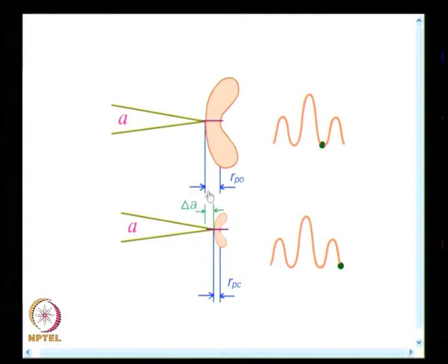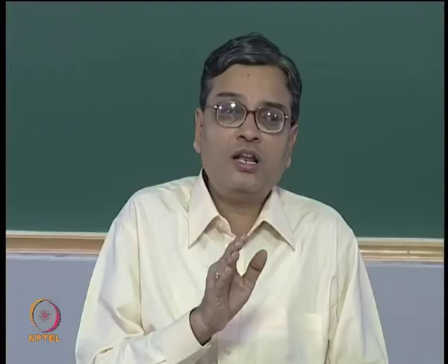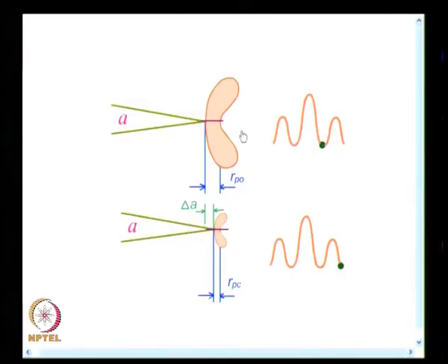Mind you, these are all highly exaggerated pictures. These are very, very small when you look at the actual specimen. For the sake of clarity, they are blown up and you have to respect it that way. So, what you have here is at the end of overload, what is the kind of plastic zone size you have. After the overload, only the crack and its plastic zone is shown. The earlier graph showed superposition of this diagram over this. Now, these diagrams are drawn one after the other to show the parameters. You will have delta A plus RPC. And the addition of delta A plus RPC would be smaller than RP naught, and it depends on what is the level of overload. If the overload is very high, then you will have a larger value of RP naught and the corresponding retardation also will be higher.